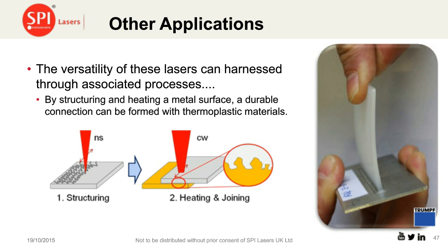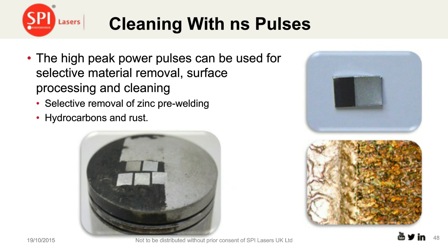Other applications are things like cleaning with nanosecond pulses. The high peak power short pulses can be very good at selectively removing material for pre-processing. For example, the selective removal of zinc pre-welding. And this is just an interesting example. Here you've got a piston head, and this was sent in to us from someone in India who wanted us to try and remove the carbon coating that was on the piston head. And what's interesting is with these nanosecond pulses, we can remove totally all the carburization, all the hydrocarbon, all this kind of debris or gunk that's been on these piston heads, down to the metal without removing the machining marks.